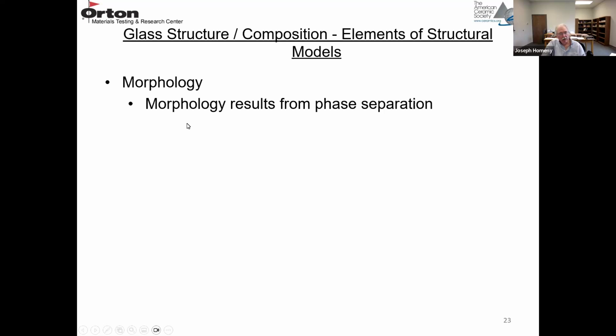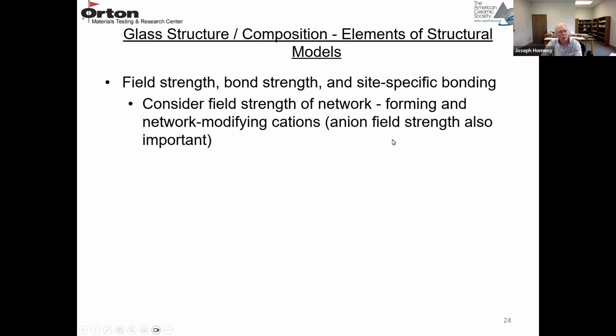Glass can have morphology. Two glass liquids can form. They can form phase separation. They can even have a small amount of crystallization. So when you have phase separation, you develop a morphology in the glass. And we talked about field strength and bond strength. So we need to consider the field strength of the network. So forming and network modifying cations, we have to consider the anion field strength as well as the cation field strength. And that has to do with the Sun's theory.